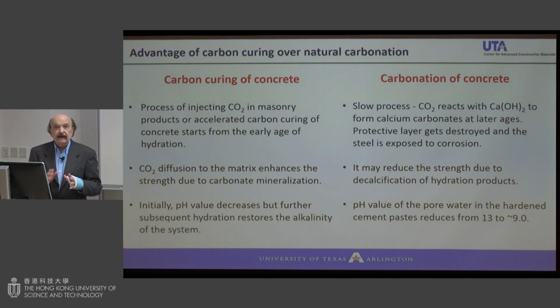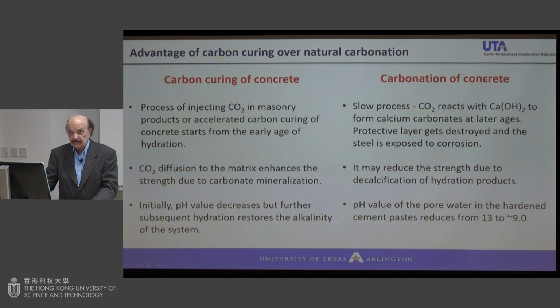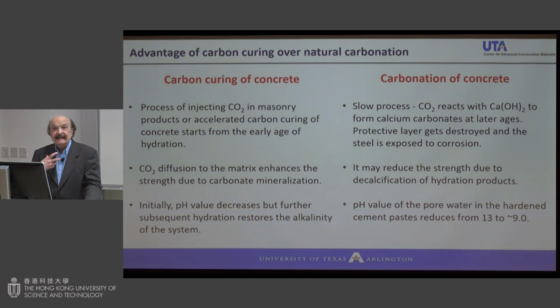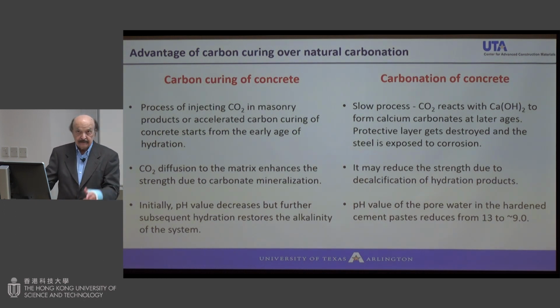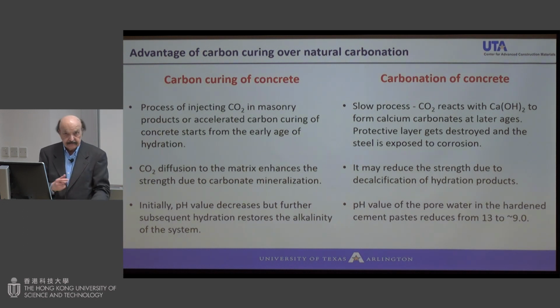Many of you know that naturally exposed concrete will absorb CO2, and we call that carbonation. In fact, carbonation is considered to be harmful, although it takes a long time. Because of carbonation, you can have a decalcification of CSH, which is not a good idea. Also, if the pH is reduced, then you have an issue with the corrosion of reinforcing bar, which is one of the major issues, for example, in the workshop that we are going to attend this weekend.